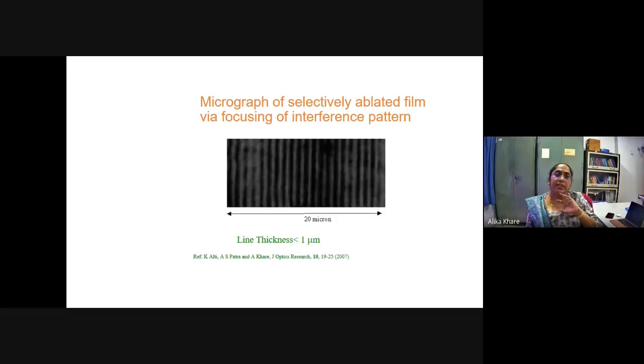One can see that within a length of 20 micron, we have slightly more than 20 fringes, so the line thickness was less than 1 micron here. In this way, one can write a fine structure, and this is just the parallel line, the one-dimensional writing.